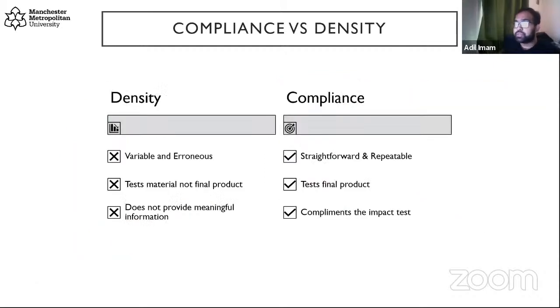Our findings from this study showed that density as a regulatory material property is quite variable or erroneous. You only test the material, not the final product, and usually our foams are stuck between two layers of fabric, and it does not provide any meaningful information. Whereas compliance, on the other hand, is quite straightforward. You can write a program on a universal test machine and it would do the test for you. You test the final product, the material and the fabric in combination as to what a player would wear during the game, and it complements the impact testing. So one is a low-speed compression test, one is a high-speed impact test. So we published this, and it is an open access paper in the sports engineering conference.